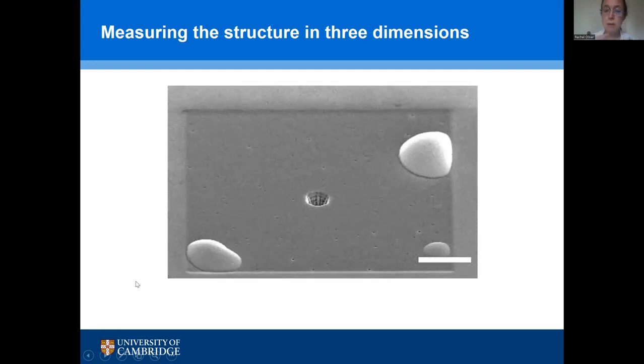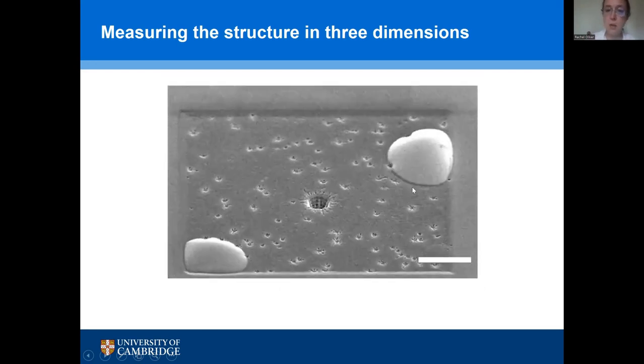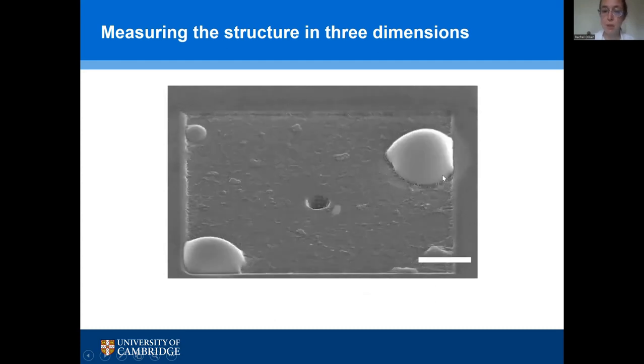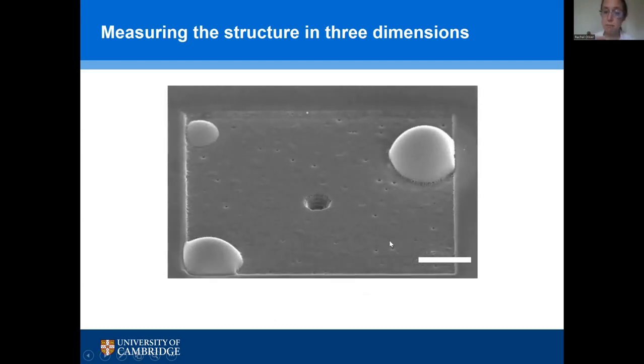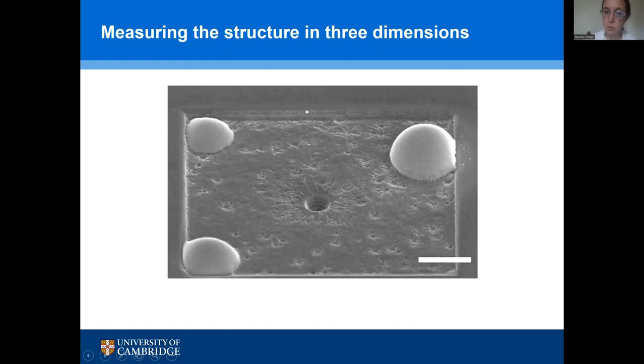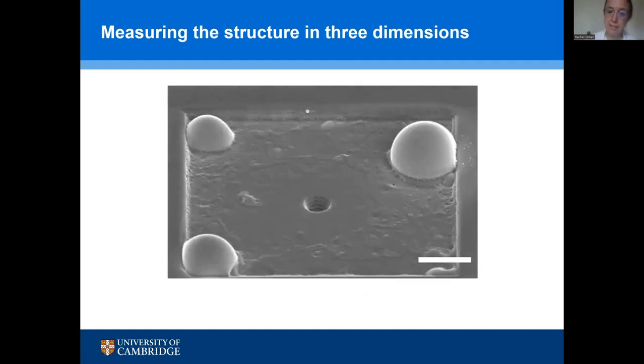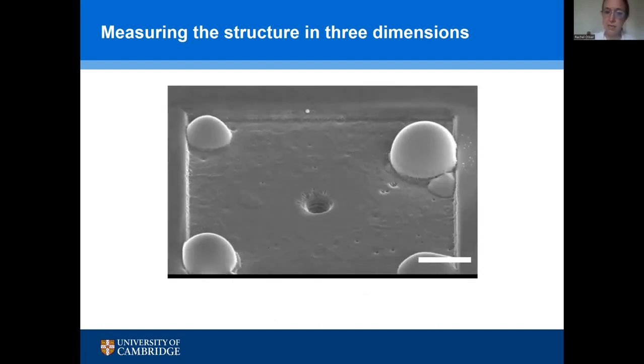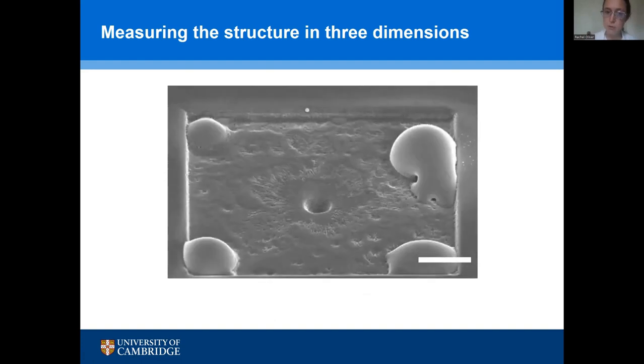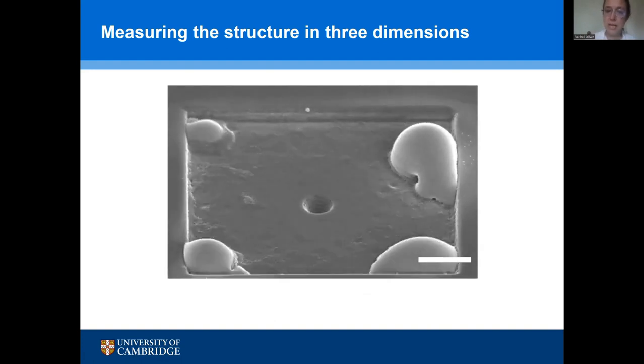So here we go, milling down through the layers. We're forming big droplets of gallium because of this milling process, but you can see there's a non-porous layer. Here's another porous layer appearing. We're milling down through that to another non-porous layer, back into the next porous layer, and onward down through the crystal.